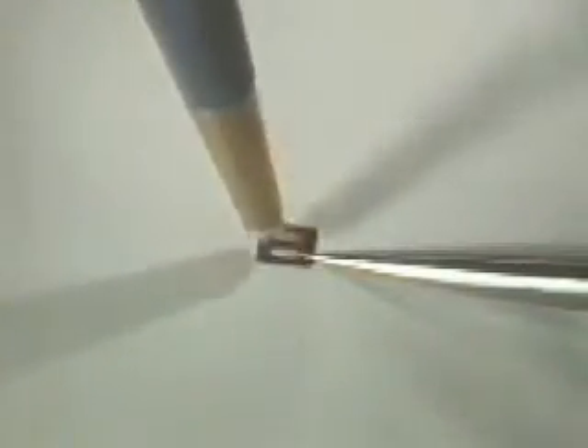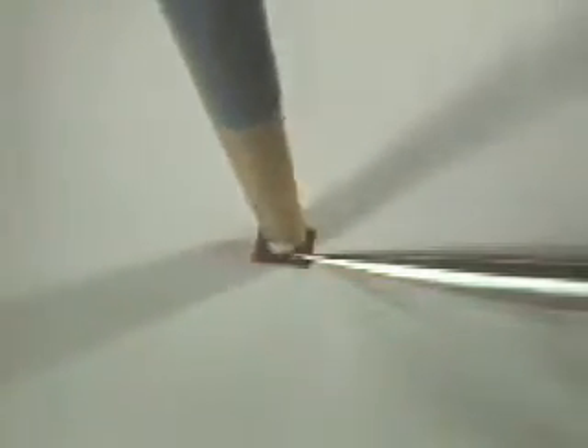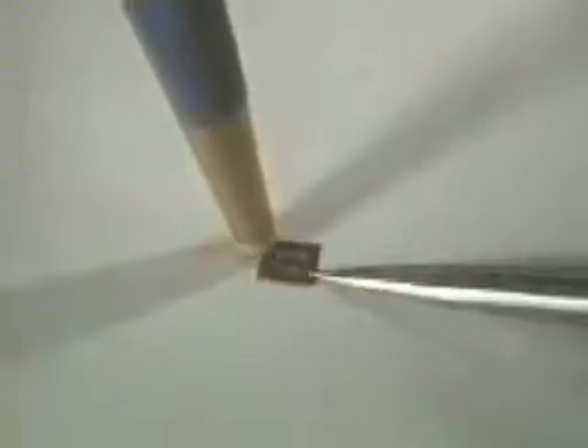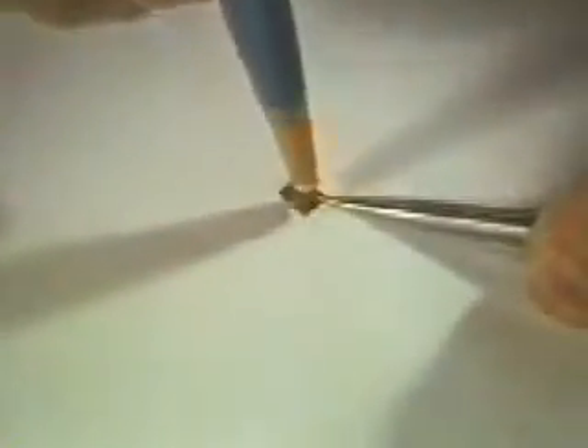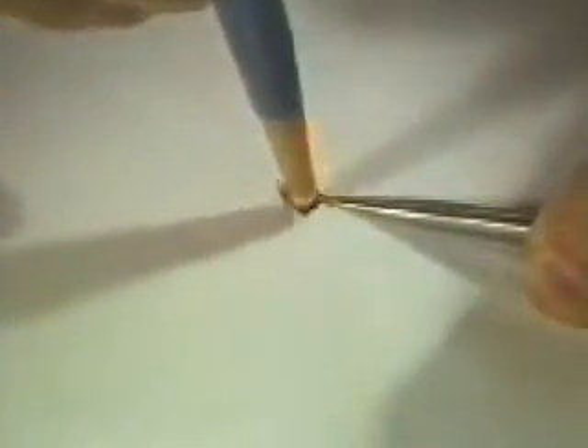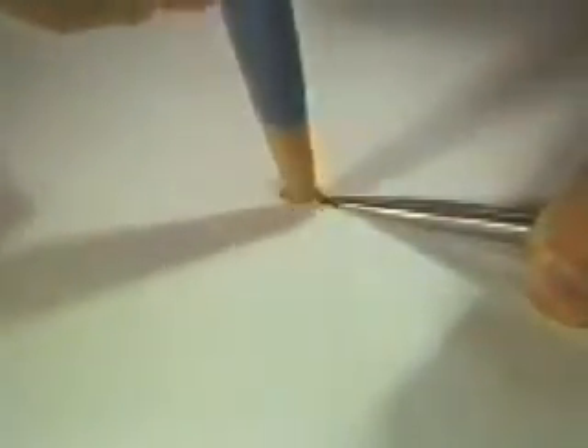Proper soldering needs a clean surface free of oxide. Therefore, the oxide layer on the metal surface can be removed, for example, with a glass fibre brush. In order to prevent contamination, all the steps are carried out on a block of clean paper sheets. When the top layer becomes dirty, discard it, and you then have a clean surface in front of you.